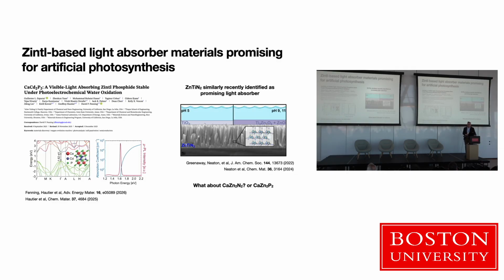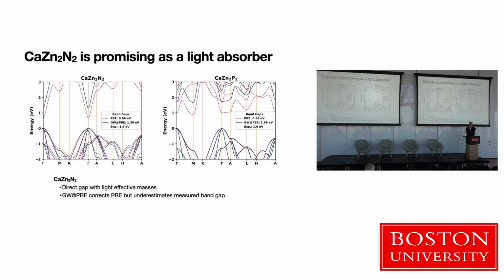Now we've done some work on zinc titanium nitride, a separate material, and so we wanted to look at some nitride-based, zinc-based materials in our data set. Part of the issue with these photo-oxidation catalysts, water oxidation catalysts, is that they have to be stable, and compatible with passivating materials and such. So we were taking a little bit of a hint. This is part of what we're putting into our prompt still. We're taking a little bit of a hint from our intuition on previous systems, and zoomed in on these calcium zinc nitride materials. I'm just going to give you a couple of preliminary results.